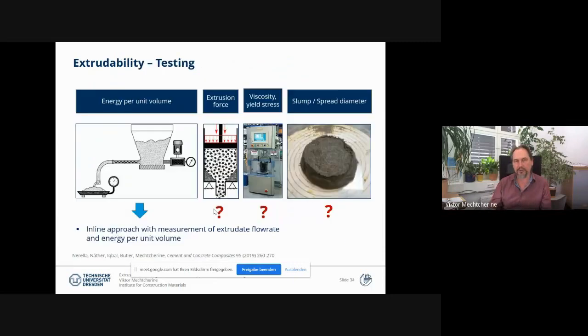So it brings me to, again, a little conclusion. With respect to the testing, we still have to develop meaningful approaches to predict the extrudability. And at the moment, the most, let us say, accurate procedure is to use the same type of extruder as you use for the actual printing for characterizing the material. Then you have really a very accurate prediction of your printing process eventually.